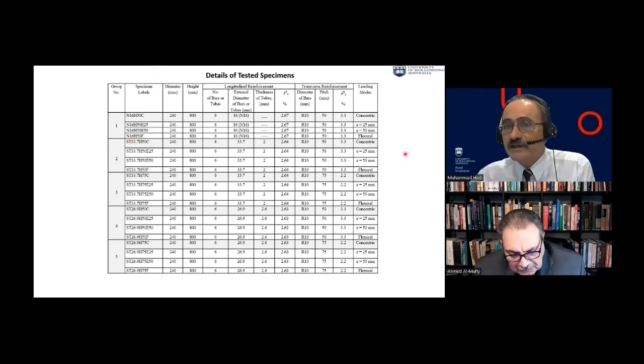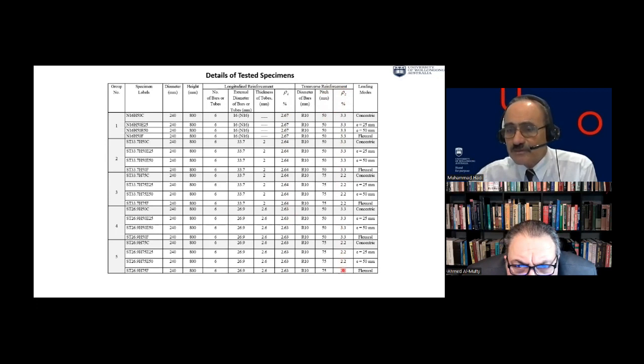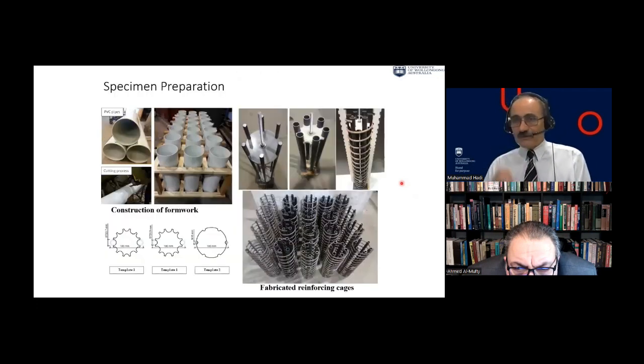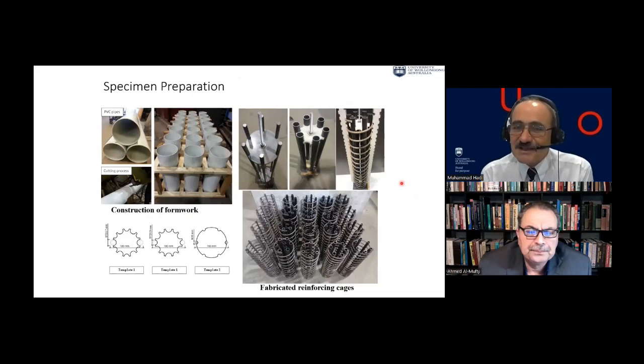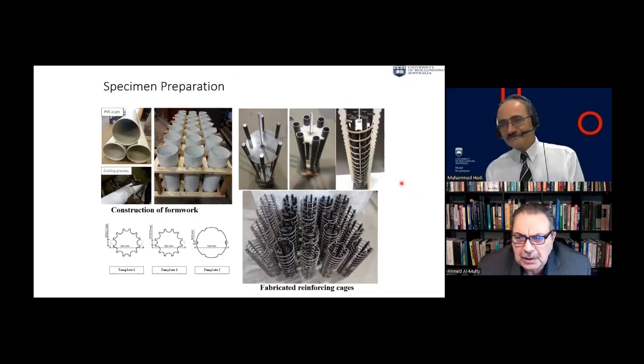Now for the reinforcement ratio, we try to keep them the same. And for the lateral reinforcement ratio, you can see there is a difference between them depending on the spacing. So we took all those into account. This percentage is by volume, of course. By volume. Yeah. By volume.